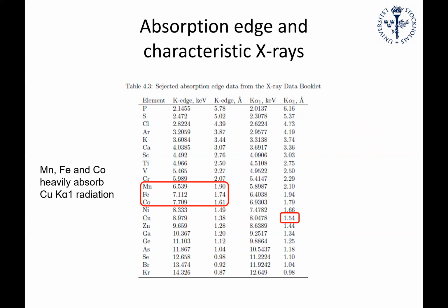And again, this is the advantage of synchrotron radiation. If you do have samples with these elements, you can tune the wavelength of the X-ray beam, so it's not a wavelength that is particularly heavily absorbed by your sample.